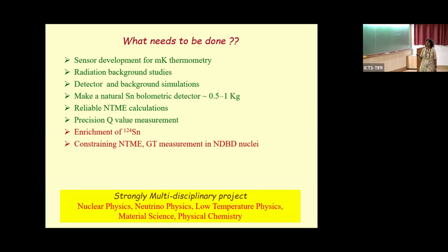Now, we tried doing a laser-based isotope separation, but we didn't quite succeed in that. So this also has to be done in a centrifuge. I put that in red because someone will definitely have to go back to Russia. Most of the double beta decay experiments which use enriched isotopes, all of them come from Russia. And we need to get reliable NTMEs, so that requires additional measurements for constraining the transition matrix elements.